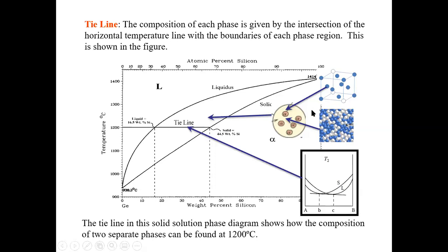And we do that for different temperatures. This will allow us to construct a liquidus and solidus that separate different phase regions, from the liquid, solid, and coexistence regions, right? This is how we construct the phase diagram from the free energy analysis. And more importantly, we showed that if you're given a phase diagram, you can recover a lot of information that you get from the free energy analysis, and even some additional information, right?